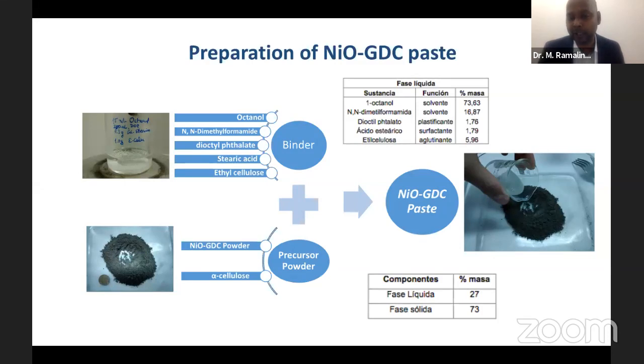This is patent work that we have filed, and recently we also have filed for a US patent. The specialty of the paste is that normally the paste, sometimes after 1 or 2 days, will lose its characteristics, like the humidity, plasticity and viscosity. But our paste, for which we have obtained the patent here in Chile and also applied for the US patent, does not lose any properties. It retains its original properties till 3 months. So that is the specialty of the paste.